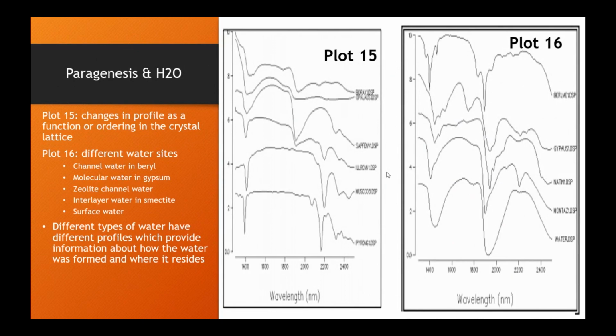So profiles also give information related to paragenesis and indirectly temperature. Broad open absorption features coupled with large water features, such as those found in smectites, zeolites, and opaline silica minerals, indicate ambient to low temperatures from low energy environments. As profile sharpens and becomes more well-defined, such as in muscovite, pyrophyllite, epidote, and dickite, the temperature of formation increases and the crystal lattice becomes ordered in a high-energy environment.